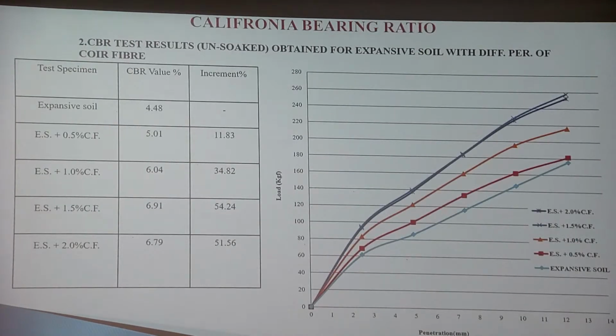CBR test result on different percentages of coir fiber. At first we find the CBR value of expansive soil, which is 4.48%. Again we increase the percentage of coir fiber with different percentages, and I found that after 1.5% of coir fiber, if we again increase the percentage, the value of CBR starts to decrease.